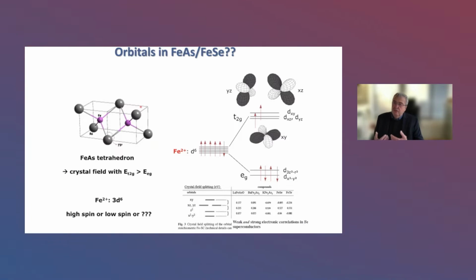If we are close to a localized state where the d electrons are not mobile anymore, of course, it's worth having a closer look at the electronic configuration in these local energy scales. And then you see this iron atom embedded within this arsenic tetrahedra. And this means you also have orbital degrees of freedom which play a role. So you have a crystal field splitting. If you then plug in these 6 electrons, you end up with these degenerate XZ and YZ orbitals. And this of course plays a crucial role. So you have this degeneracy of the orbitals.